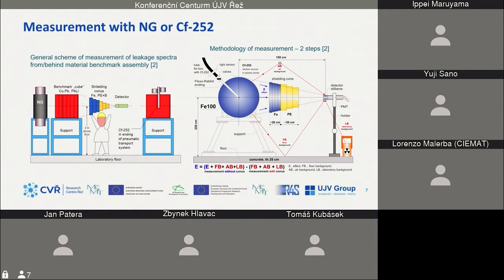Then, in the second measurement, between the detector and the assembly, we put a shielding cone, which shields the useful signal, and then, as is written here, we subtract both measurements and we get a pure signal. Of course, this places special demands on the quality of the equipment and long-term stability. But because we have 30 or 40 years of experience with it, we can guarantee that the procedure is okay all the time.